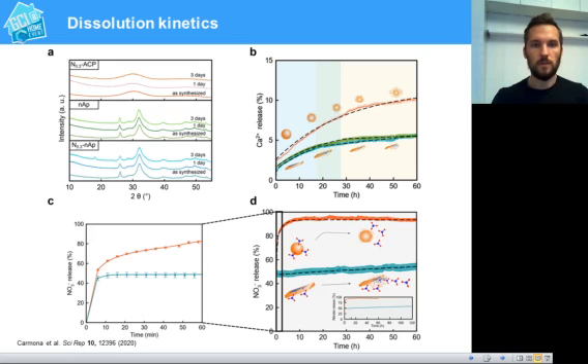Samples are definitely stable in water. They were put in undersaturated conditions. And we measured calcium release for the completely amorphous material, and the nanocomposite and the nanoplates material. The release of calcium is also indicative of the phosphate release because of particle dissolution. As you can see in figure B, calcium release for the amorphous phase is much faster than the release for the nanoplates. Moreover, the dissolution kinetics of the nanoplates follow two different regimes.